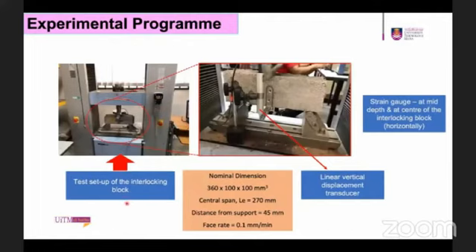Okay, this one is the test setup of the interlocking concrete block. In this study, we put one LVDT, or linear vertical displacement transducer, at the center of this interlocking block, and the strain gauge was located at the center on the other side of the block. The effective length, or span from one support to another, is 270 millimeter, and the block was loaded at a rate of 0.1 millimeter per minute.